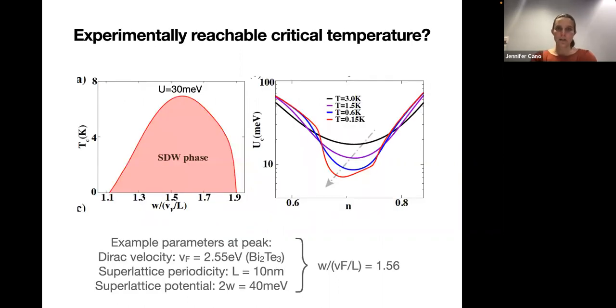And finally, the other interesting point to make is that from our calculations, we think that this Moiré lattice could actually be within experimental reach. So, for example, this is a plot which is showing, if we estimate the Coulomb interaction to be 30 meV, what's the critical temperature of the spin density wave? And so we see that the critical temperature can be as high as a few Kelvin. So that's something that can be experimentally measured.